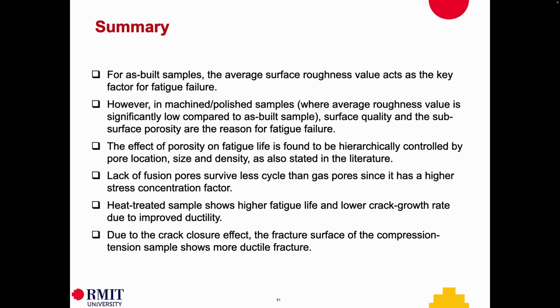Finally, lack of fusion pores could be critical for us because they are much more critical than the gas pores, which are spherical. So lack of fusion pores could be notorious defects, which can significantly degrade fatigue life. Heat treatment is a great way to improve fatigue life and lower crack growth rate due to improved ductility, but considering the crack closure effect, the fracture surface for the compression tension loading will show more fracture and we'll have a higher fatigue life. So that summarizes the findings.